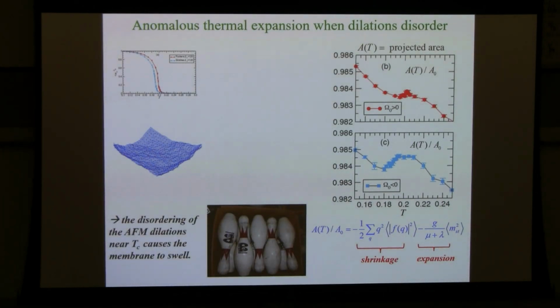Well, one analogy I like is packing bowling pins. If you're packing bowling pins in a box, you want them to be antiferromagnetic because they fill up the space very nicely. And if I randomize the orientation of these pins, the volume in this case would swell. And so near this Ising phase transition, in fact, the area relative to some reference area at zero temperature goes down, thermally shrinking, then has the phase transition. It goes up, and it goes down again.